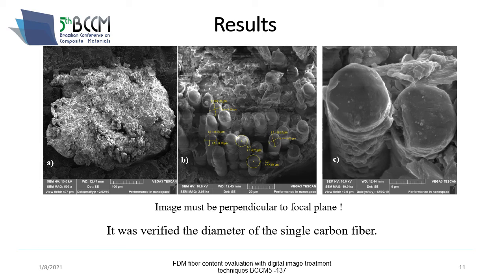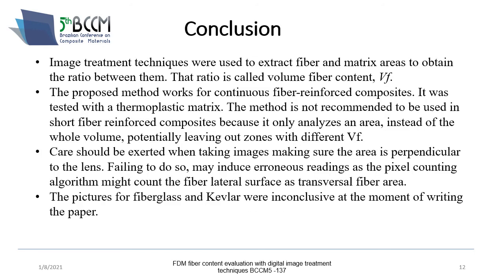Some of the results were inaccurate due to the fiber being placed non-perpendicular to the focal plane. So we can verify the diameter of the carbon fibers, the distribution, and the matrix, but it was difficult to observe the fiber volumetric fraction in images that weren't perpendicular to the focal plane.